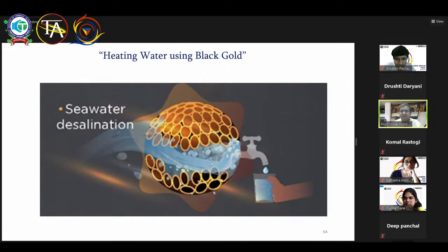You may think, oh, gold is so expensive. Why do I use the gold? Can I use some other element? Ideally, yes. We're trying different elements, but this seems to be the most active and most stable, right? You can use aluminium instead of gold or copper, but they're not stable. They oxidize and then their activity goes down, whereas gold is active and stable. And these are catalytic processes. That means once I have the black gold, I should be able to use it thousands and thousands of times. It's recyclable, reusable. So that makes the process sustainable if the productivity is higher.